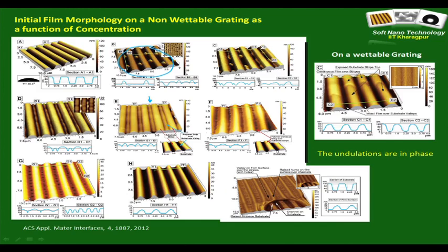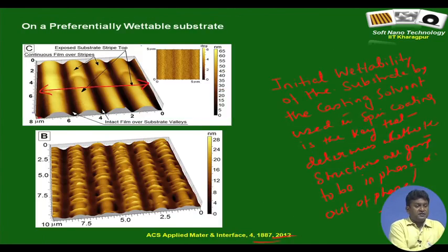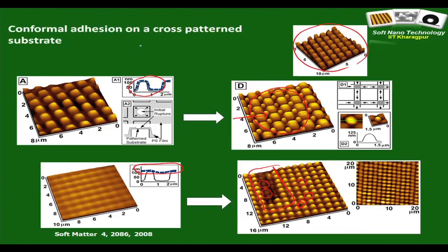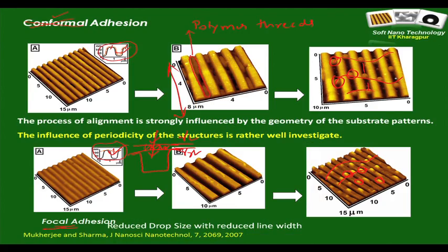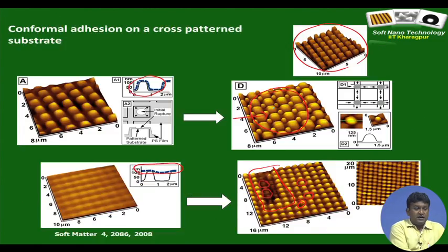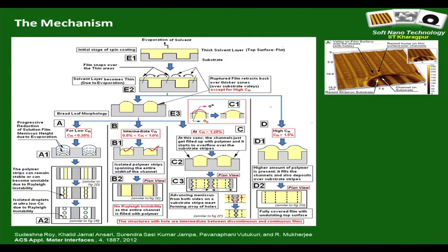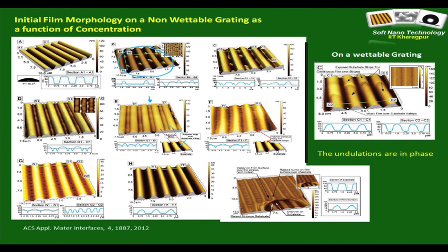And have you seen a structure similar to this one? Yes, indeed you have seen an identical structure over here, when you actually floated, transferred, or even dewetted a film for a long time over a topographically patterned substrate. So this took 6 hours, and in contrast to that, spin dewetting in fact can make the same structures in a minute's time. So that's the advantage of spin dewetting, which is a very, very recent development, and it's going to become a very popular rapid nanofabrication tool for sure.